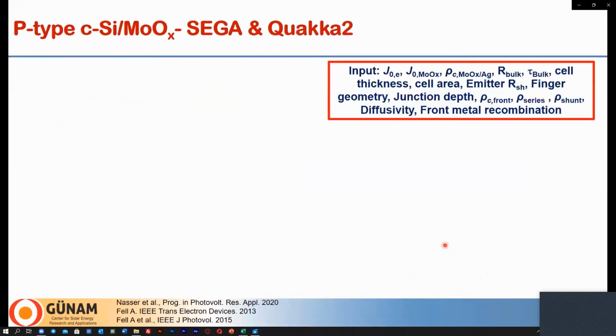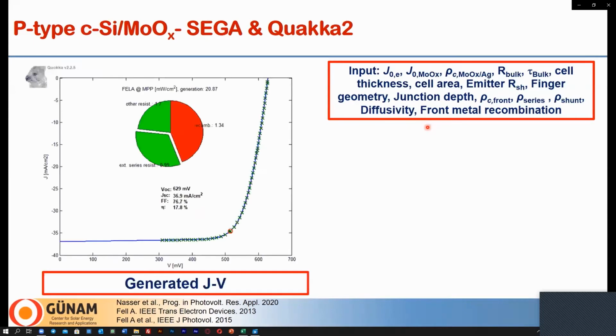Later on, in order to demonstrate the potential limit of the fabricated P-type wafer solar cell with molybdenum oxide at the back side, we performed synergistic efficiency gain analysis, SEGA, using Quakka2. Based on this loss analysis, we were able to define the dominant loss mechanisms and see how we can improve the efficiency of the industrial scale P-type solar cell with the full-area molybdenum oxide hole collecting rear contact. As an input in this simulation, we employed different optical, electrical, and passivation characteristics of each layer or each interface of the fabricated solar cell. But first, we need to reproduce the experimental results in the Quakka2 simulation tool, as shown here.